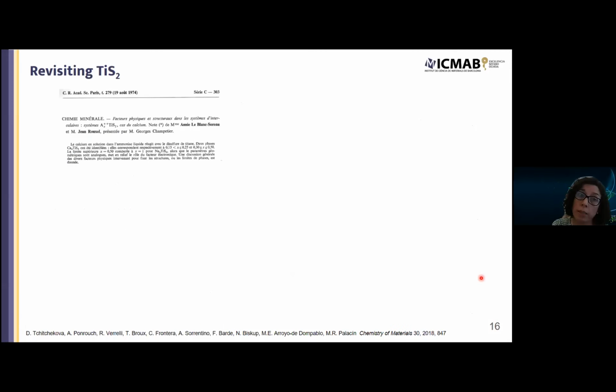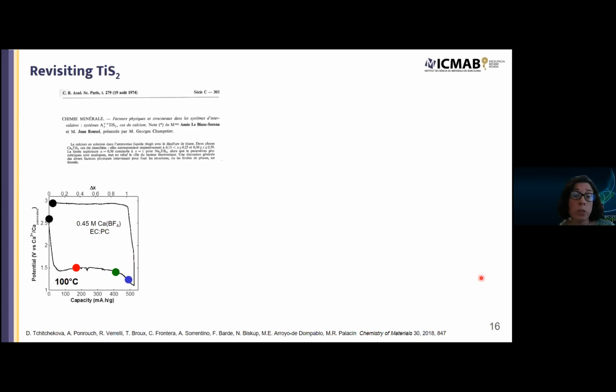So this time we decided to revisit TiS2, and there was precedent of intercalation of calcium in TiS2 by Jean Rouxel in the 70s in Nantes, in France. And they did this using calcium dissolved in liquid ammonia, and they were able to intercalate calcium in between the layers of TiS2, still coordinated by ammonia, and then by gently heating, they were eliminating ammonia. So this is what we got when we tested it electrochemically.